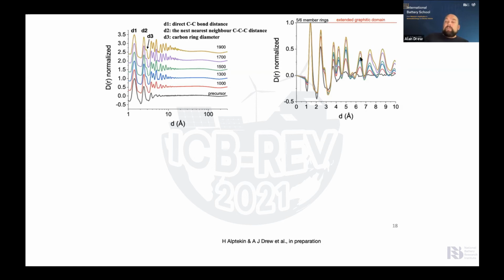This region here is the extended graphite structure. This region down here is within the ring. Okay, we can define a couple of bonds here, right? D1 corresponds to a direct CC bond distance. D2 corresponds to the next nearest neighbor CCC distance. So that's 3 carbons. Okay. D3 corresponds to the carbon ring diameter. This little shoulder there, right?